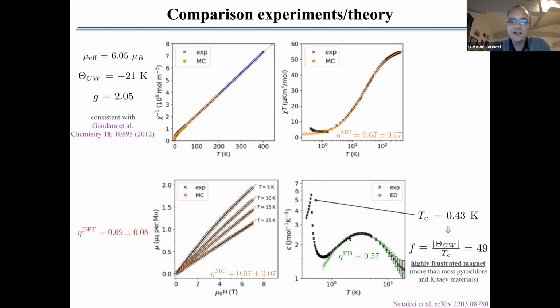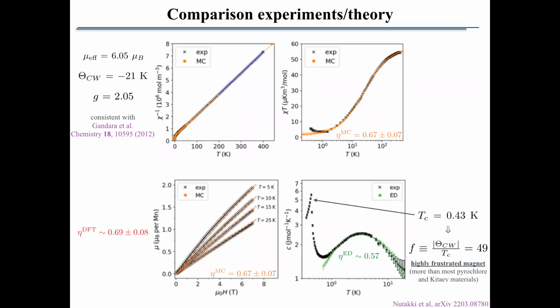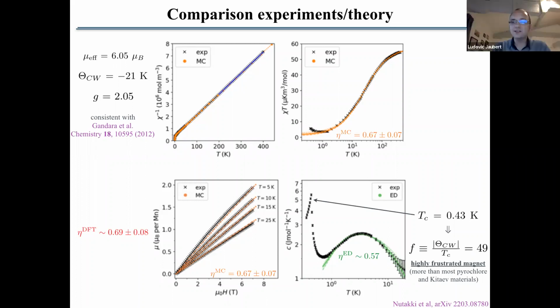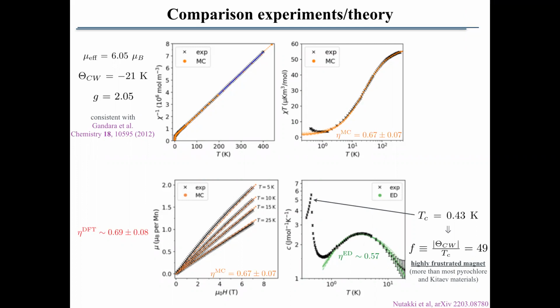We have measured. So this part here is actually the magnetic contribution of the specific heat, because of course they measure the whole specific heat, but they have also measured the specific heat for the non-magnetic equivalent sample, and by subtracting the two with the correct coefficient, you can get rid of the phonon and lattice contribution, and you can just get the magnetic one. So this one is just the magnetic one. Thank you. So this one is indeed essentially the onset of magnetic correlations. Okay, thank you.